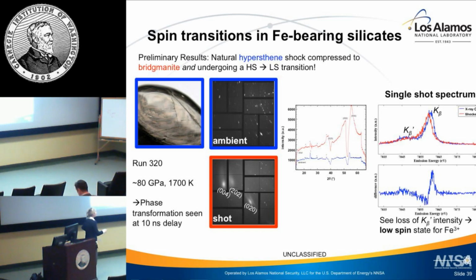If we look at the emission, I know it's a little bit hard to see, but the X-ray only is in blue, and you can still resolve your K beta prime in the blue, but in the red trace it's a little less. It's more pronounced if you look at the difference pattern here. In other words, we are going through a spin transition. So this is really remarkable. We have two different data sets that show structural transition and spin transition in the same shot.